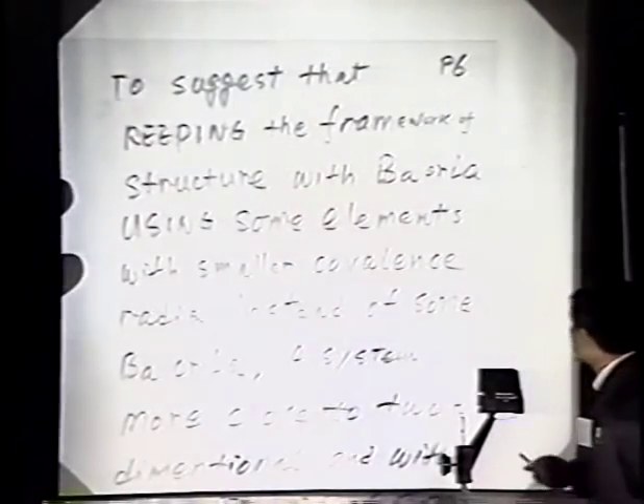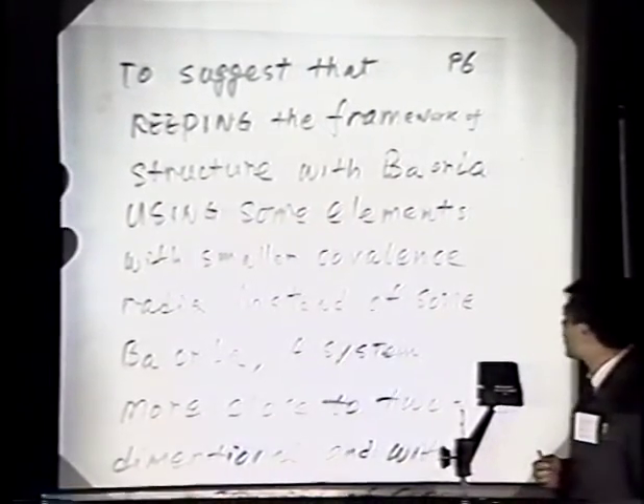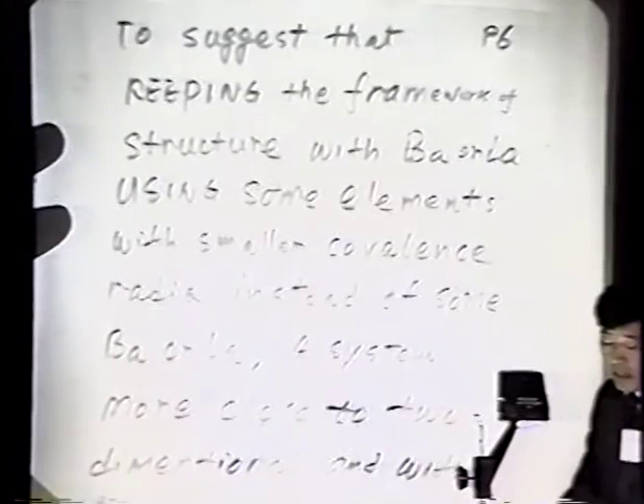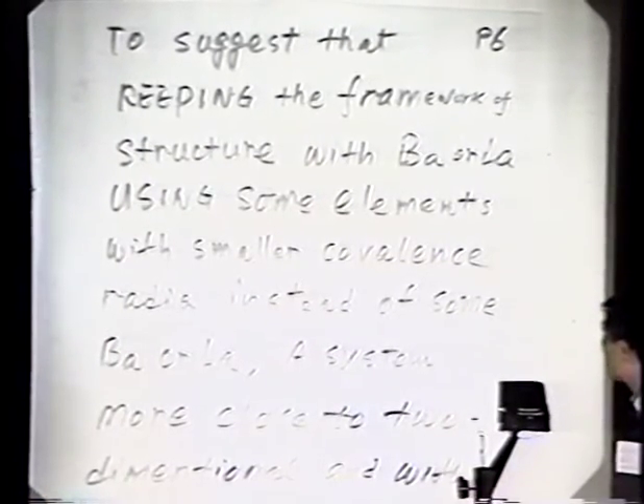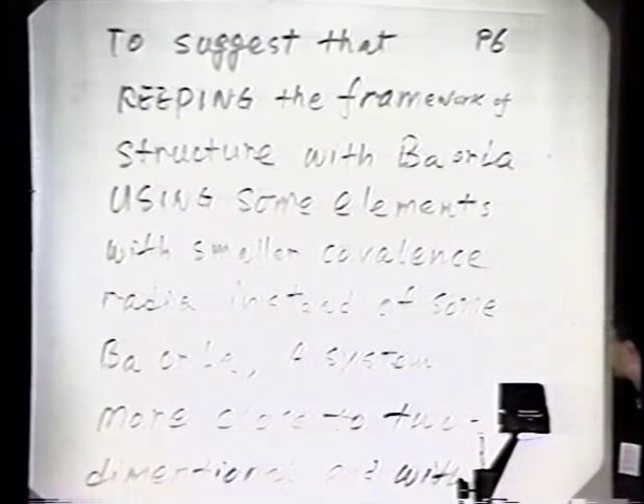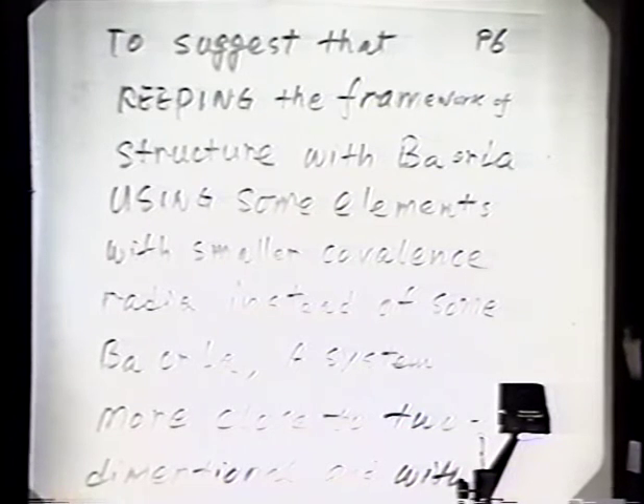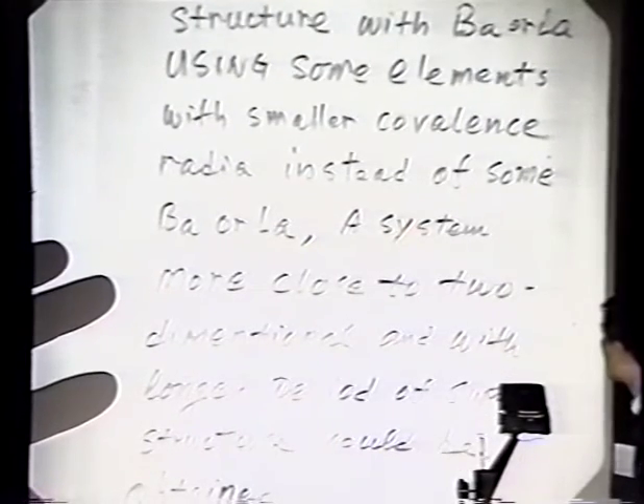Because these materials are known to have a layered perovskite structure, we suggest keeping the framework of the structure with barium and lanthanum, and using some elements with a smaller covalent radius instead of some of the barium and lanthanum. A system closer to two-dimensional, with a longer period of superstructure, could be obtained.